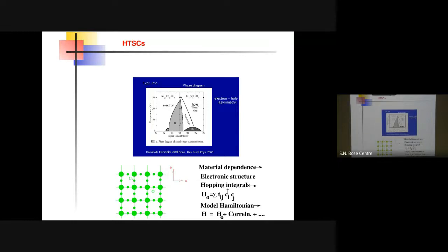And what this phase diagram shows is that you can electron dope as well as hole dope, which is shown here. But unfortunately, in the same material, you cannot both electron dope and hole dope. They are different. And without the doping in this copper oxygen plane, this is an antiferromagnetic insulator. And as you increase the doping, a superconducting dome appears with a dome-like shape, as you can see. People have an idea that the superconductivity has to come from the strong electron-electron correlation, but the precise nature of the driving mechanism even today is actually debated.